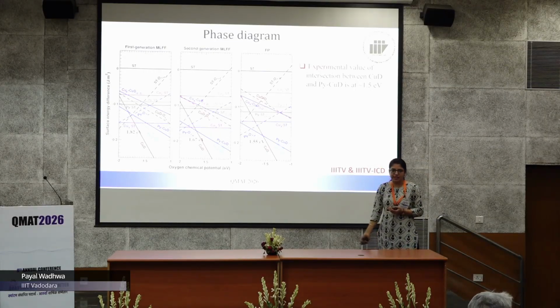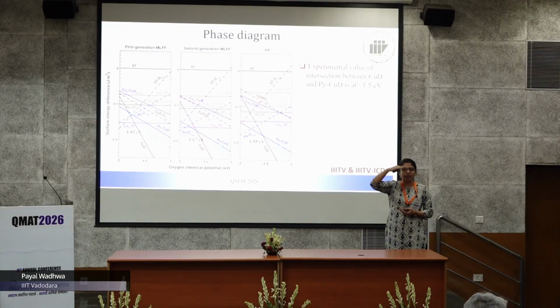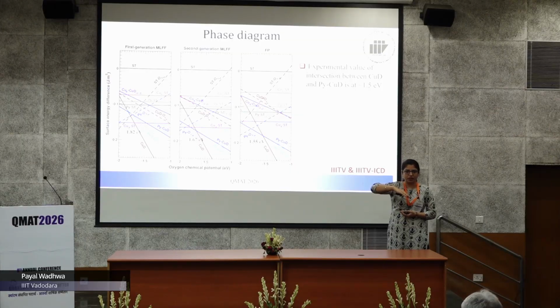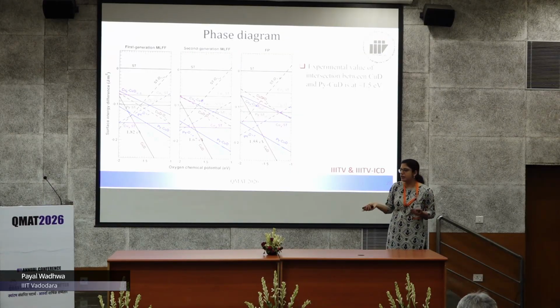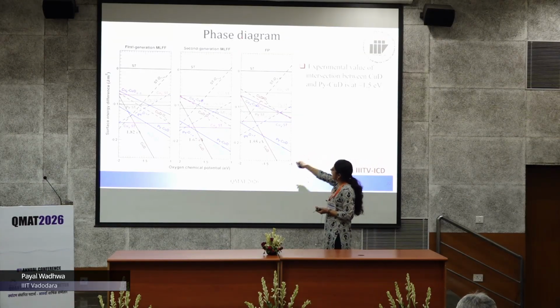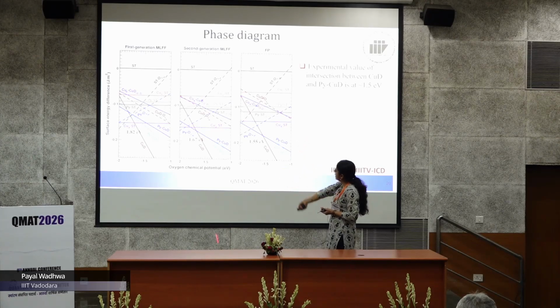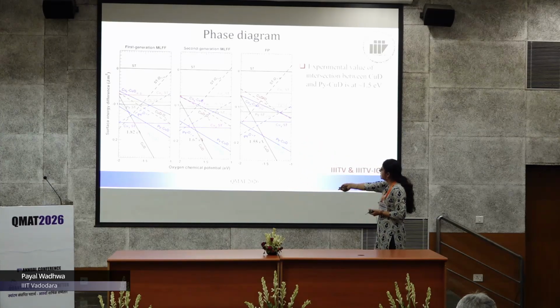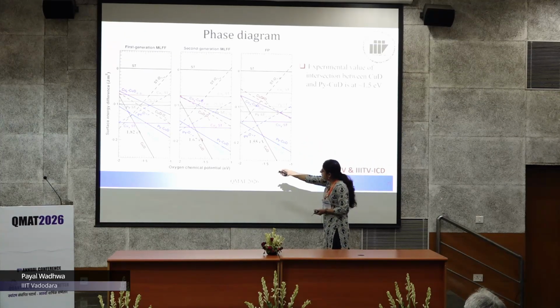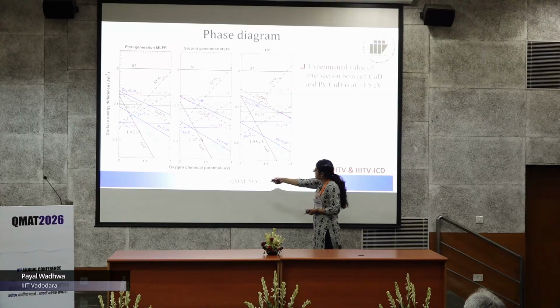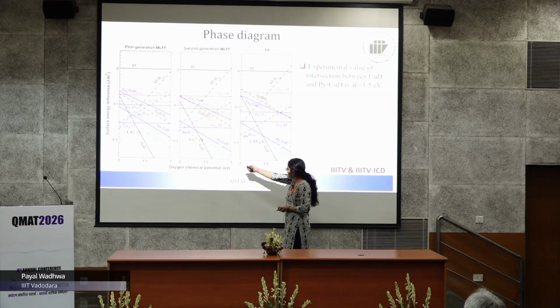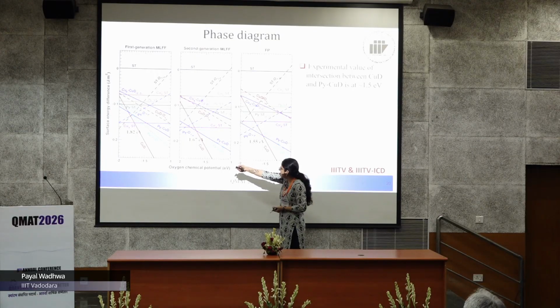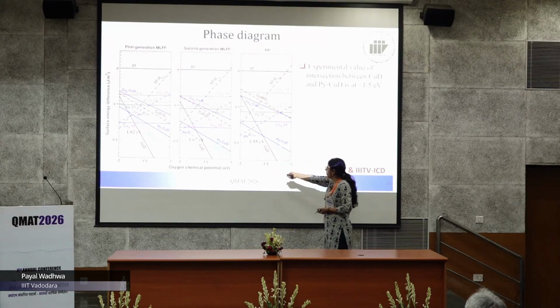Then we plotted the phase diagram. You have ground state energies of various configurations, right? But which one is actually the most stable one? To determine that, we plotted the phase diagram using first generation force fields, second generation, as well as first principles. Of course, the lowest one would be the most stable one. You can see here this copper deficient and this pyramidal copper deficient. This blue one and maroon one have an intersection at minus 1.67, and here it is at minus 1.55.